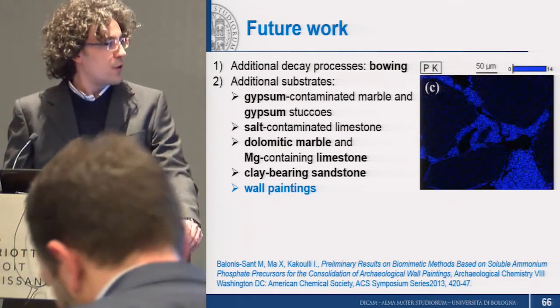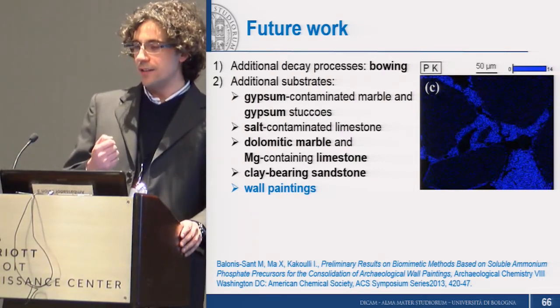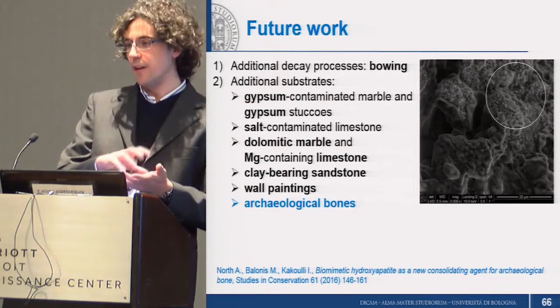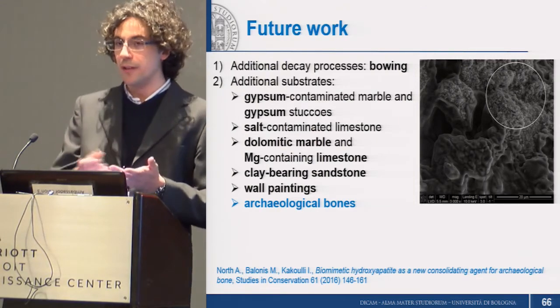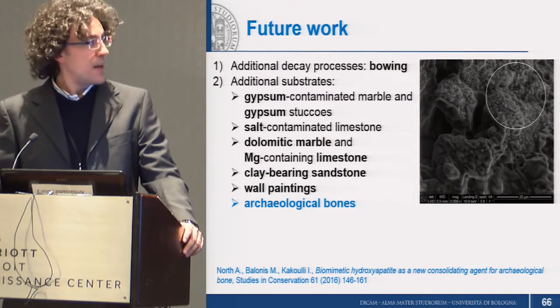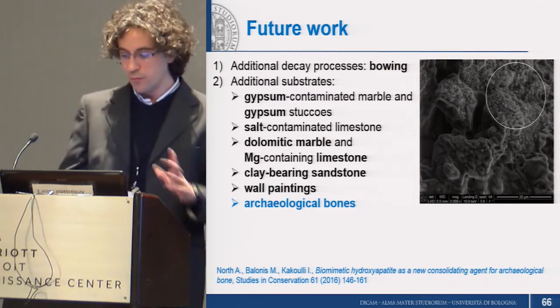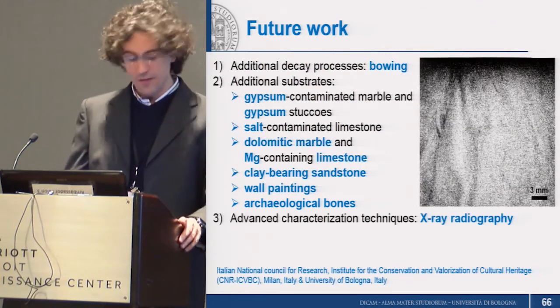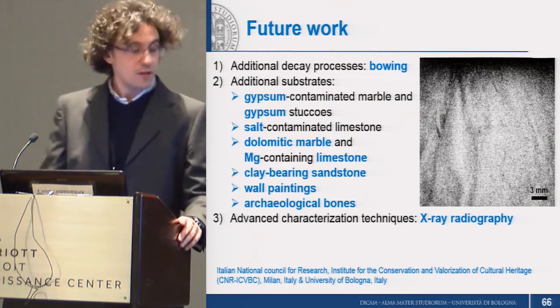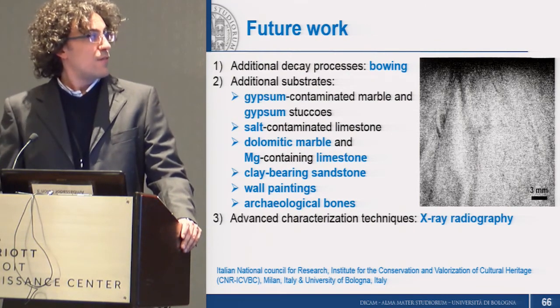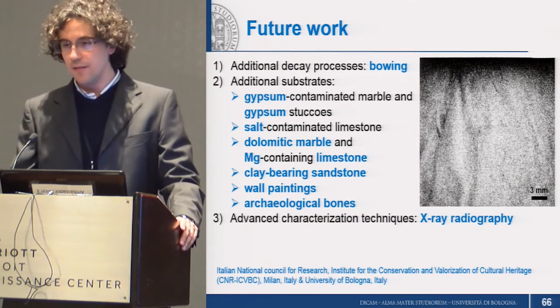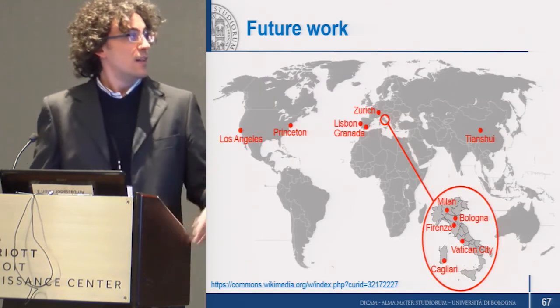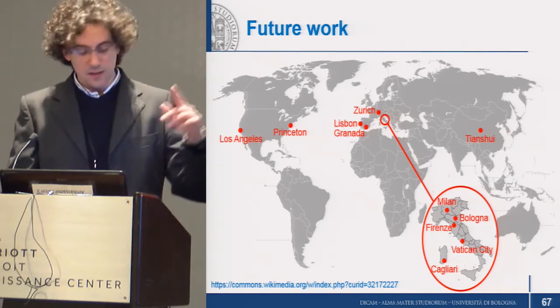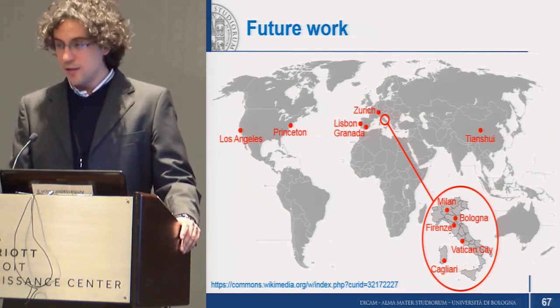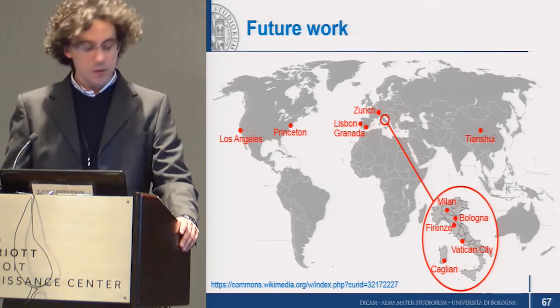And also recently for archaeological bones, which is another interesting aspect because bones are mainly made of hydroxyapatite, so using hydroxyapatite to consolidate hydroxyapatite would be the perfect fitting match. And we are now also starting to use more advanced refined techniques to find out the effectiveness, for instance, the distribution and the penetration depths of our treatment. And then finally, I think it's quite a positive and good opportunity for us that nowadays several groups around the world, and especially in Italy, have started investigating this treatment, which means that some fruitful collaboration can be established between different groups, which is positive.